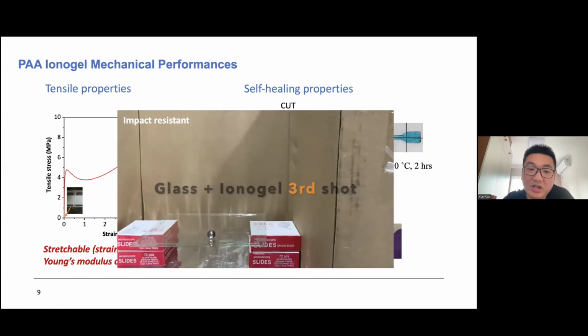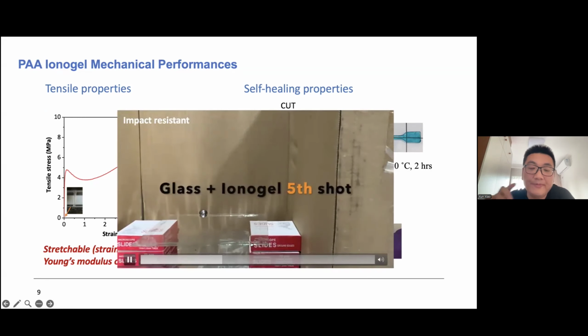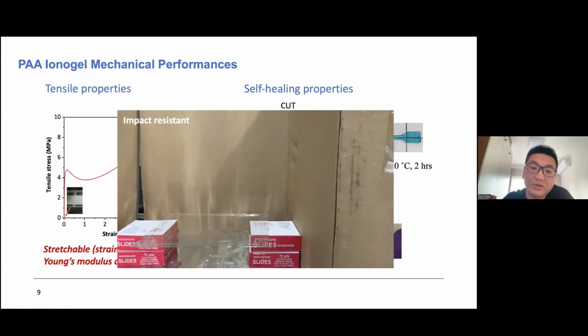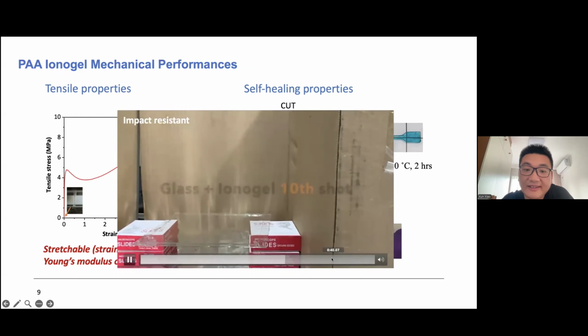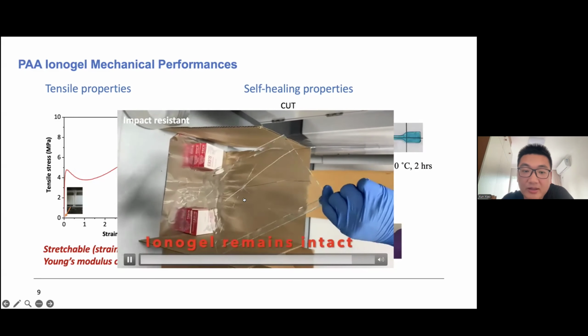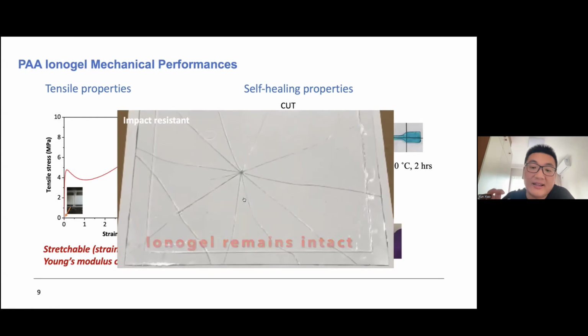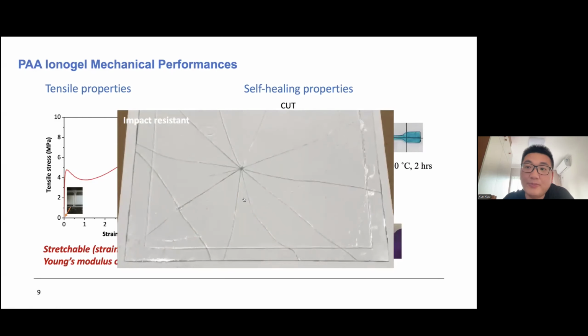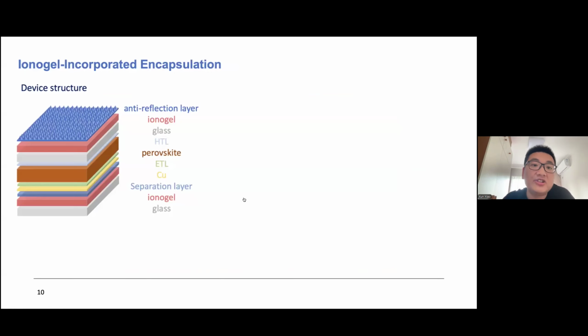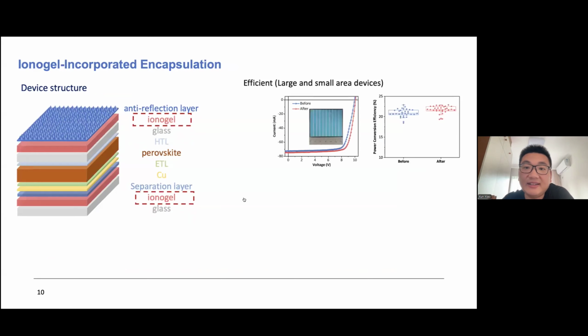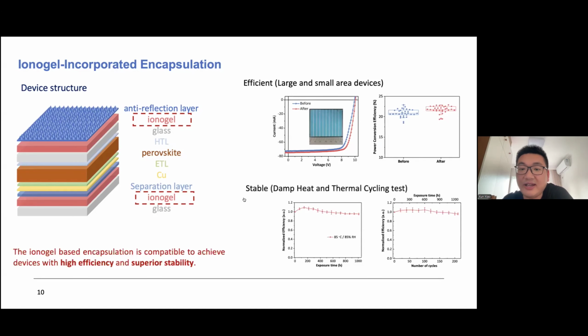And if we use glass with ionogel, so this is glass, and we have a layer of ionogel on top, it can now resist the metal ball dropping test. We have tested for more than 14 times, and then the glass finally breaks. But our ionogel can still keep the sample intact. That means it will not break into pieces. So we incorporated this ionogel into encapsulation. We first tested the efficiency, because we don't want this encapsulant to be damaging to our perovskite solar modules. And we found it is very good for efficiency and stability. It can be compatible with our high efficiency and stability.